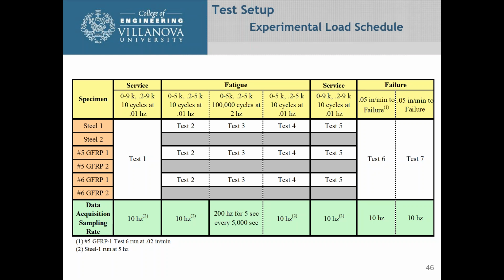The next tests were 3 different tests for fatigue loading. We changed the loading to fatigue loading. We run 10 cycles very slowly with the fatigue loading on it. Then we go and apply 100,000 cycles at a much higher frequency. And then the last 10 cycles we do very slowly again. And what we're going to do with this is compare what happens after 100,000 cycles. Then we apply the 10 cycles of service load on it, and what this ends up being is a comparison.